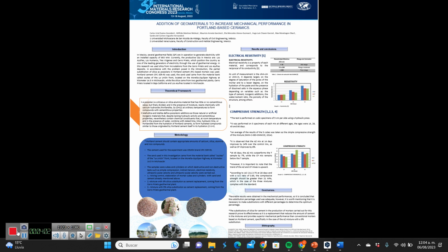Now, analyzing the compressive strength test, the test was performed on cubic specimens of 5 centimeters per side using a hydraulic press at the different ages. The ages were 14, 28, 45, and 90 days. It is observed that the Azufres plant mix at 14 days improves by 24% over the control mix, as well as Cerro Prieto improves by 8%.